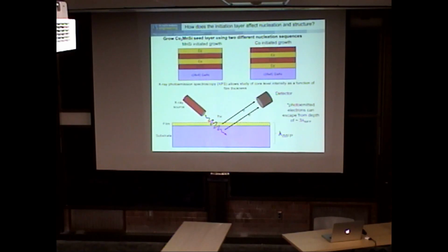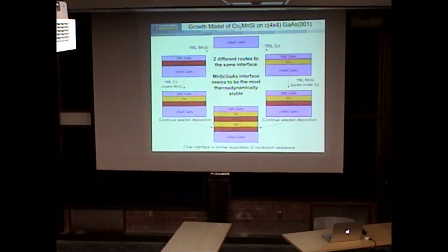One of the experiments we've done is to use X-ray photoelectron spectroscopy, since we have this in our system. We're going to grow it atomic layer by atomic layer and use the XPS to measure the signal from the film and the attenuation of the signal from the substrate. This is a very surface-sensitive technique. We're going to do one where we start with manganese silicon first, then cobalt, then manganese silicon, then cobalt. And the other one, we're going to go cobalt first, manganese silicon, cobalt, manganese silicon. I'm just going to summarize the results.